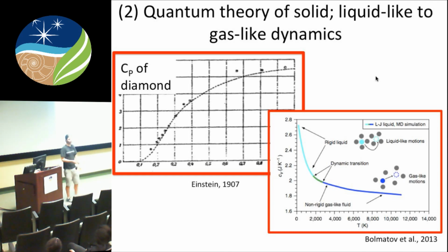But there's new possibilities. Like one set of proposals from researchers recently, and maybe going back a few decades, that has very little experimental testing, is how does the heat capacity change from the classical limit of 3R, here's 2.8 R, down to the ideal gas limit of 3/2 R. And there's some theories of how that would happen, how that would relate to viscosity and shear modulus, but they've largely been untested because of lack of data.